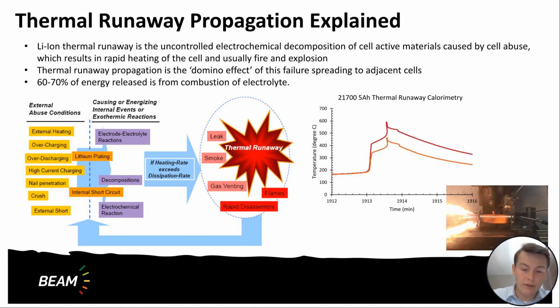So thermal runaway is the uncontrolled excessive heating of a cell caused by abuse conditions to the cell, whether that be overcharging or external overheating. It can also be from mechanical damage such as crush or nail penetration, as well as any external short circuit damage to the cell. It can also occur without these due to manufacturer defects in the cell. So if a separator is folded or something like that, like what has happened recently in the news with LG and GM, that can naturally lead to internal short circuits during various conditions.